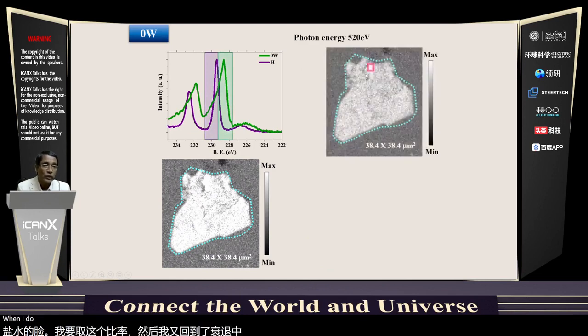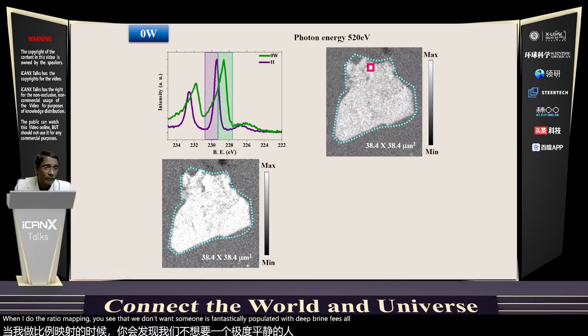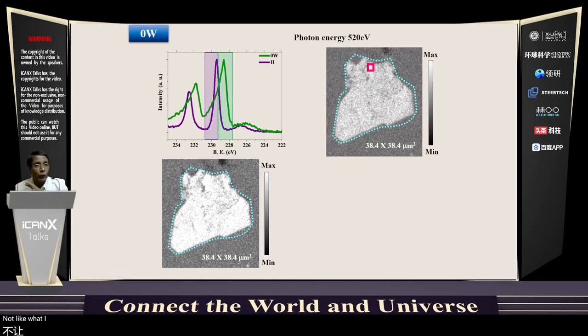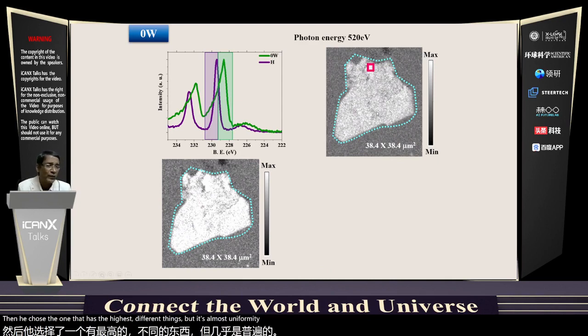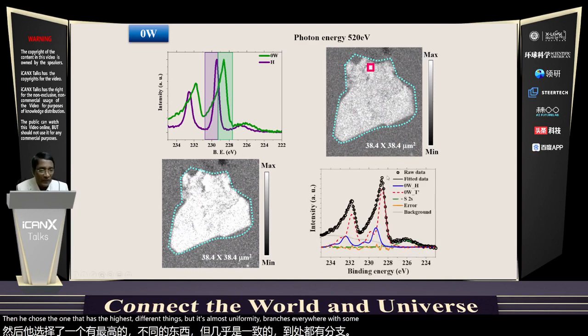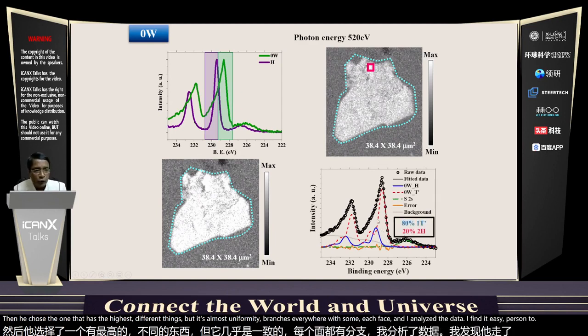When I do the ratio mapping, you see that the zero wash sample is fantastically populated with T prime phase all over, not like what I showed you before, which was a little bit in some places. There we chose the one that has the highest T prime phase, but here it's almost uniformly T prime phase everywhere, with some H phase. I analyzed the data and I find it's 80% T prime phase and 20% H phase.